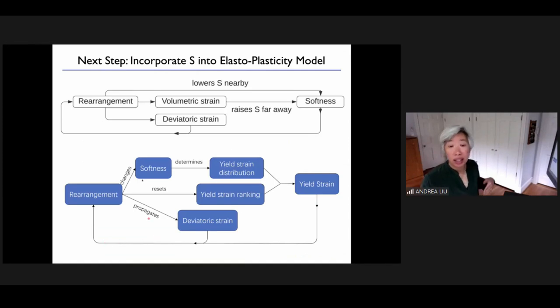So now we can incorporate this into a lattice model. That's the idea, that we could take this and get away from these particle-based simulations and put it on a lattice and see if we can understand what's happening. So we put it on a lattice, we allow the rearrangement to change a softness, which is assigned to each lattice site. The softness determines the yield strain distribution, and the rearrangement also gives rise to a deviatoric strain, which combined with the yield strain determines whether we have another rearrangement.